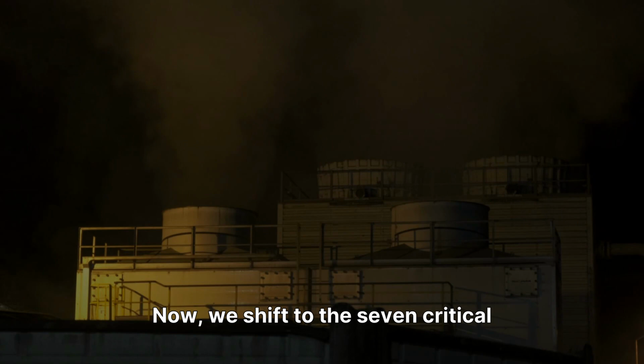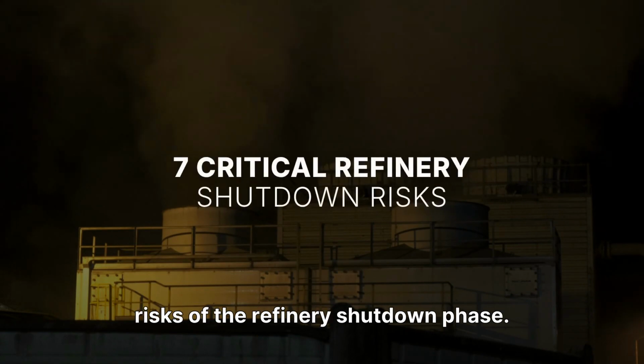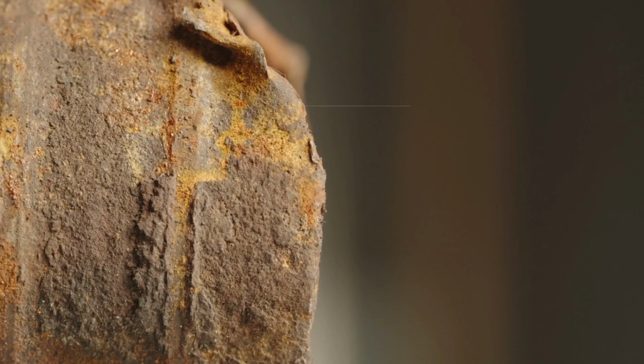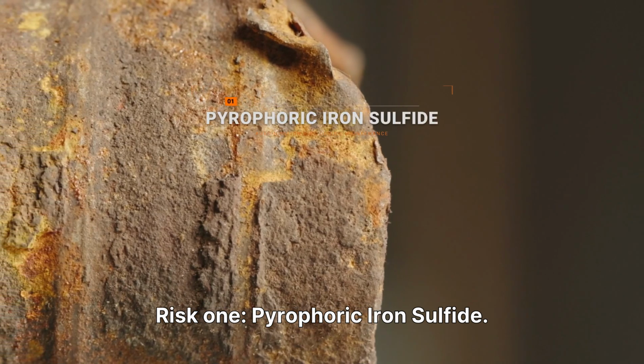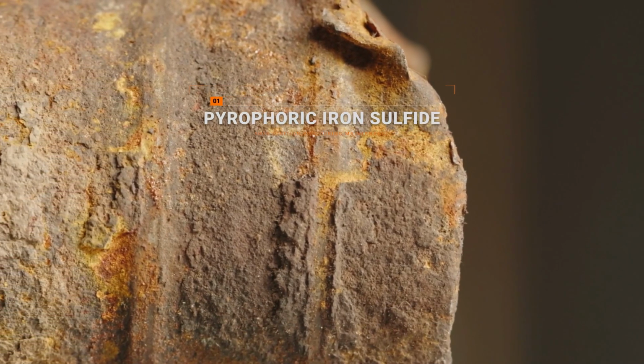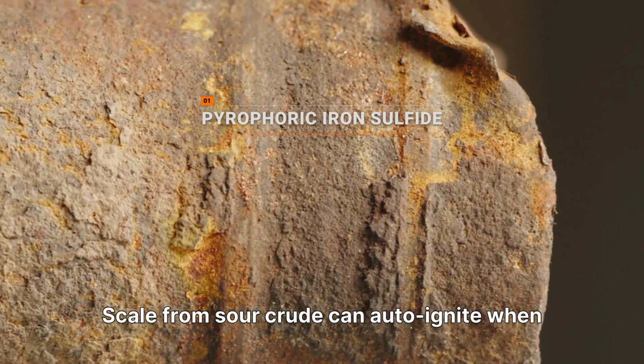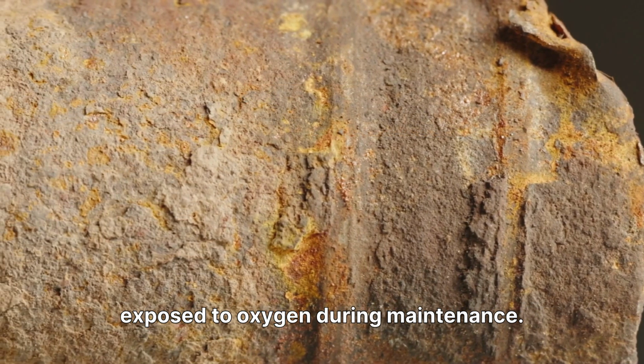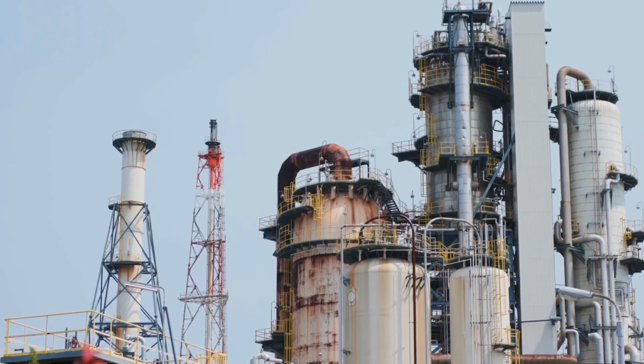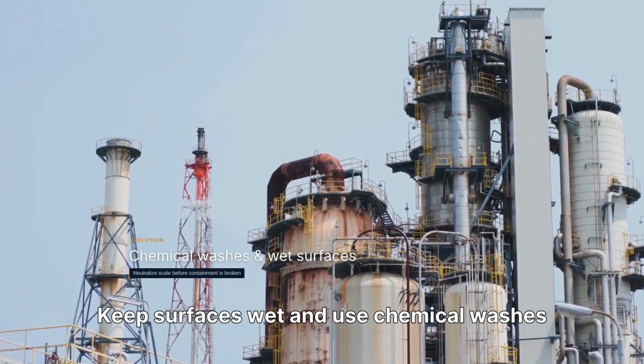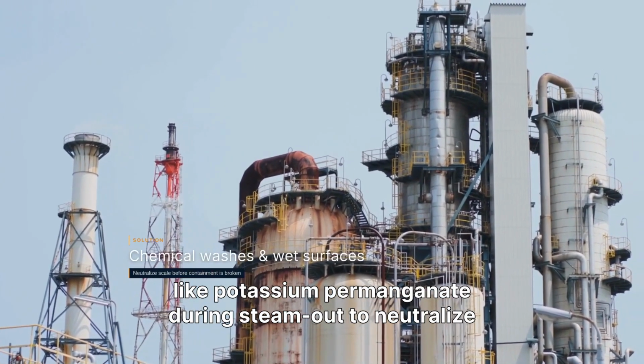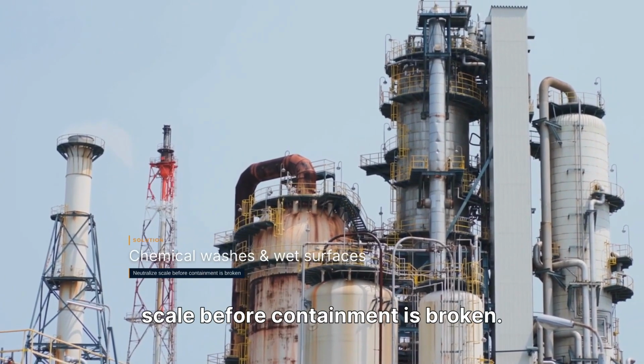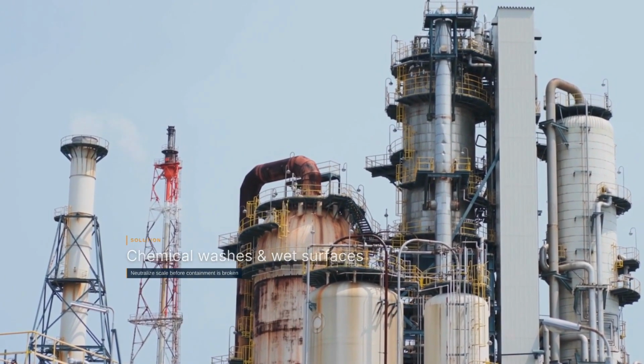Now we shift to the 7 critical risks of the refinery shutdown phase. Risk 1. Pyrophoric iron sulfide. Scale from sour crude can auto-ignite when exposed to oxygen during maintenance. Keep surfaces wet and use chemical washes like potassium permanganate during steam out to neutralize scale before containment is broken.